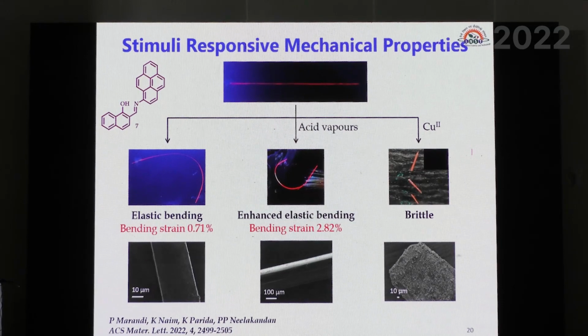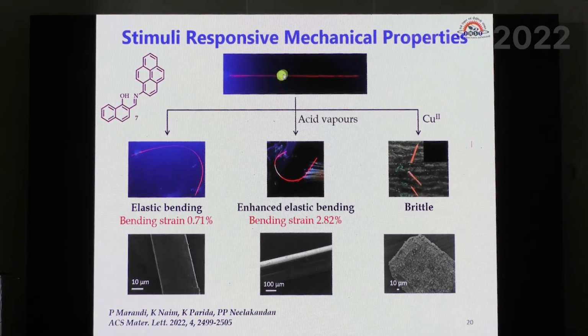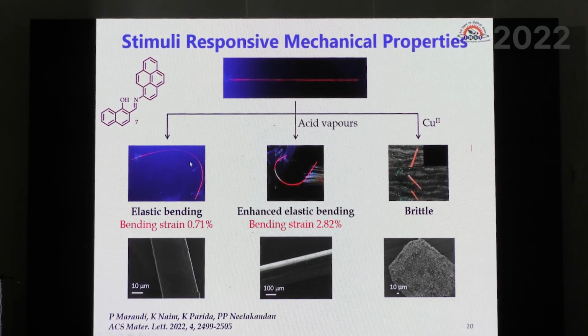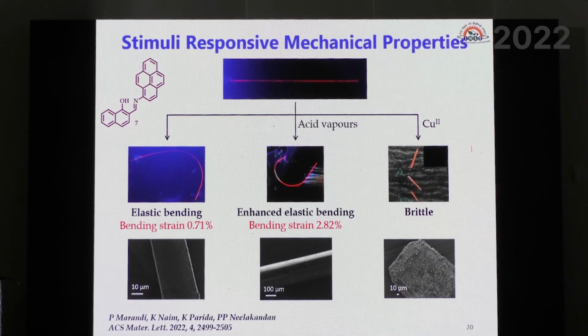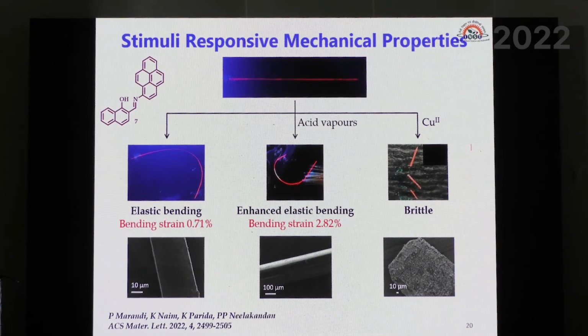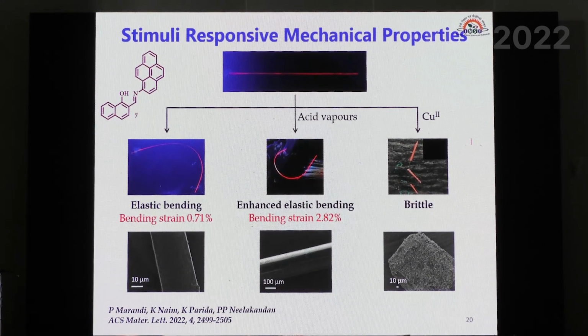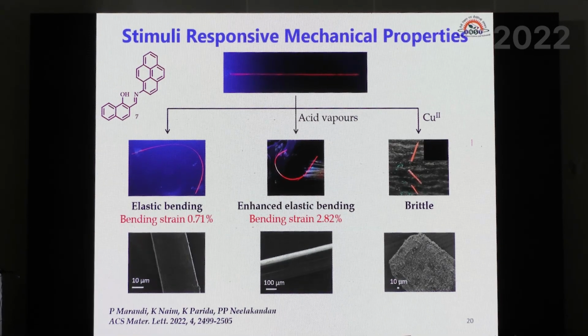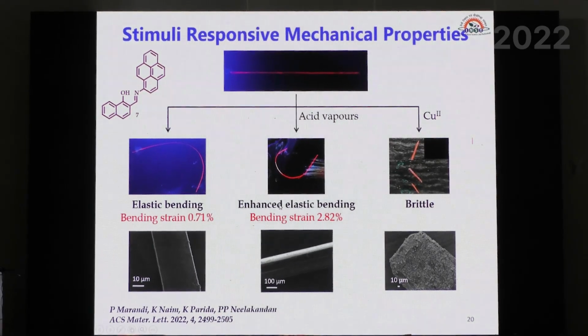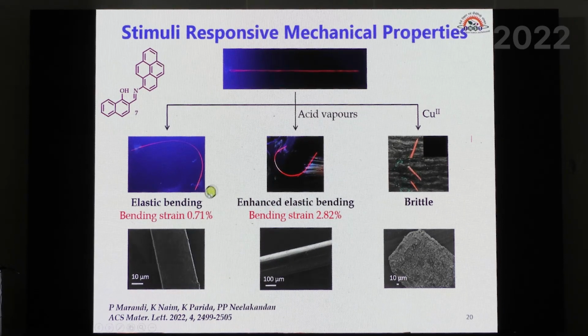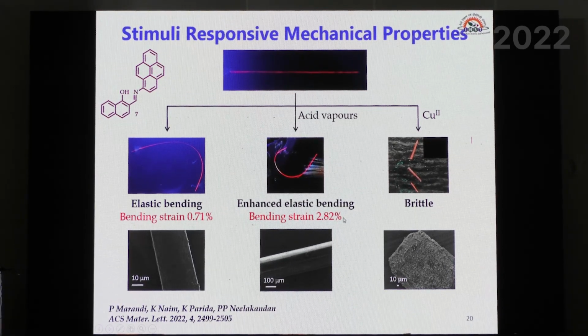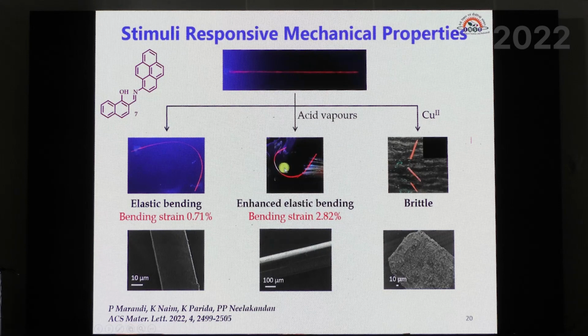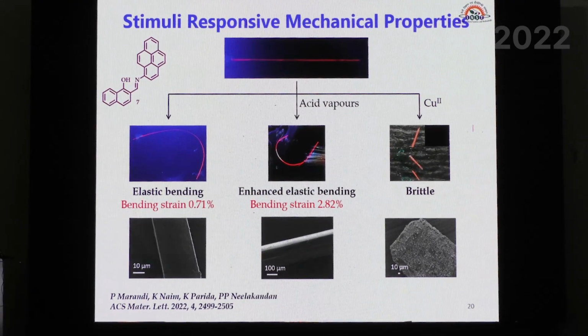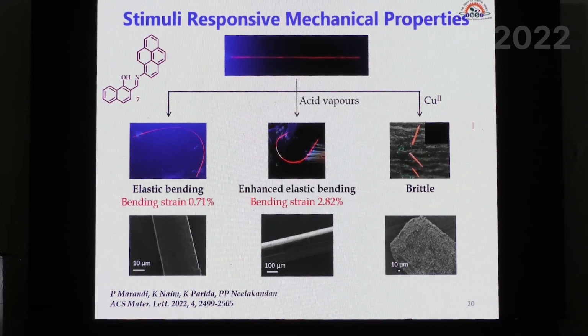So what we have studied here: initially, this is the photograph of a crystal. You can see it can be bent. It shows elastic bending. That means if you bend it and take out the force, it will go back to the original straight form. We also calculated the bending strain. And when you expose it to acid vapors, it becomes more flexible. The bending strain increased from 0.7% to 2.8%. And the color also intensified a bit because the acid probably protonated the imine there, and as a result, you end up with a little better fluorescence.